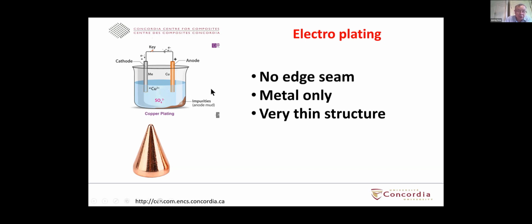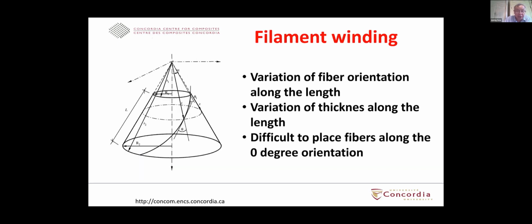This method certainly has no edge, but it can only be used for metal. And in the case of electroplating, you can only manage to get very thin structures, something like a fraction of a millimeter. For composites, people have also made composite cones.